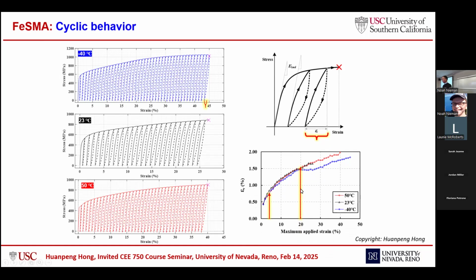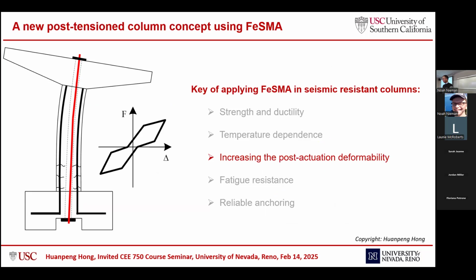Another thing we learned here is that as the loading cycle and the loading amplitude increase, this recovery strain also increases. This is important because it reflects the transformation degree of this material. When we increase the loading amplitude from 4% to 20%, the recovery strain almost doubled. Based on this finding, we found a way to increase the post-actuation deformability of this material.